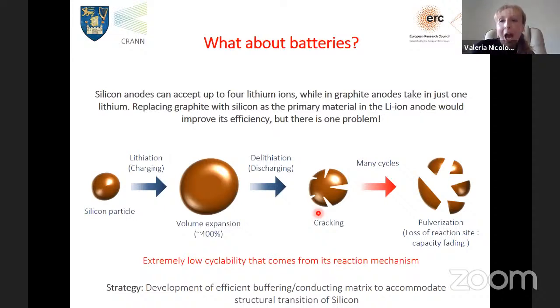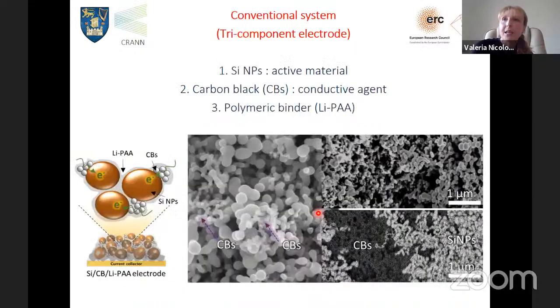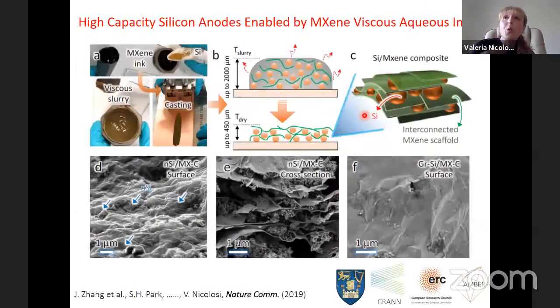So what we thought was, well, how can our 2D materials help this? And there are some solutions out there in the literature. For example, one way was to mix the silicon nanoparticles with carbon black to give conductivity to the electrode, and a polymeric binder that is supposed to give more mechanical stability to the electrode. But this is not a very good solution. So what we did was replacing the conductive additive and the polymeric additive with our MXenes. And we could do it by simply mixing the two things together, silicon particles and MXene inks, make a slurry, and then cast it onto a copper foil, which is our current collector.